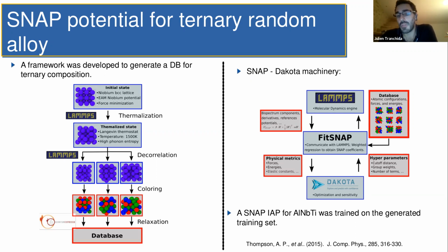I usually try to have, for those kinds of studies, mean absolute errors for the energy below 100 meV, milli-electron volts per atom on average. So not excellent errors, but sufficient for the work we're going to be doing here. Also, I don't use a testing set. I only have a training set here, because the SNAP potentials are rather simple. They don't have tons of parameters, so you shouldn't have a lot of overfitting, and it's not always super necessary to have a testing set in that case. At least that's what I've seen so far.